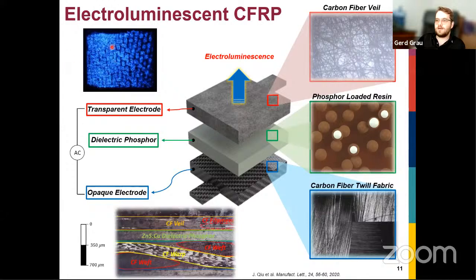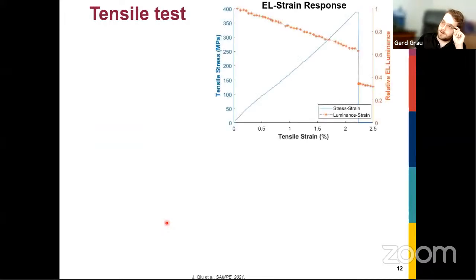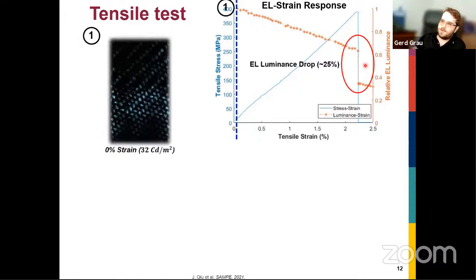And so here you can see we get a nice light output after some optimization. And in this cross-sectional view, you can see the structural carbon fiber, the phosphor, and the mesh. And so we did a uniaxial tension test. You can see that we have a standard stress strain curve, but as our strain increases and stress, of course, our light output decreases. So you can actually then visualize the strain by seeing if your light output changes. And once we hit the failure point where the stress just drops, our light output also drops. So you can see this here. This is with 0% strain.